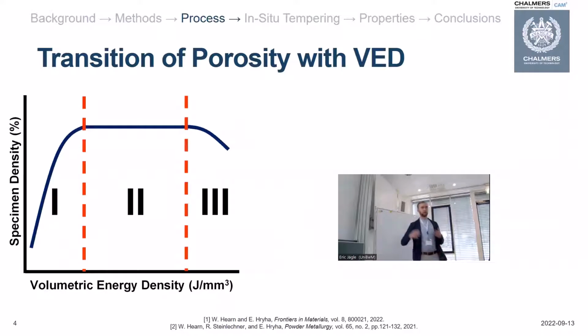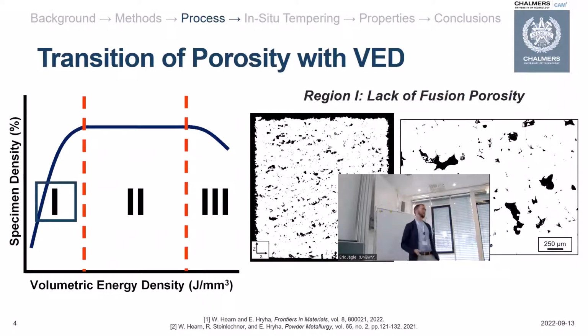So jumping into the first part, I'll talk about the process window we saw for these alloys. Generally for the carbon and low alloy steels, the density of your specimens was related to your volumetric energy density. I think it's quite well established and would follow this schematic that you see here. So we found specimens produced at low energy input would have very poor density, as you'd have many large and irregular pores related to lack of fusion porosity.